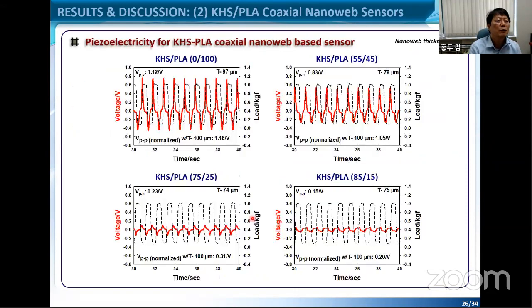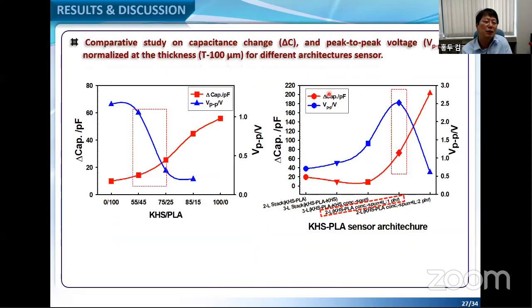value. In terms of piezoelectricity, of course, the PLA 100% gives the highest signal because it is a pure PLA system. But as you increase the KHS, the signal is going to be smaller and smaller. But at about 50%, the signal is not that small. Of course, the absolute value is about 0.8 volt, but it's not that bad. So in this case, 50% KHS and 50% PLA is, I think, one of the good choices. So from this result, I can say that for a coaxial system of PLA with KHS, about 50% KHS is, I think, a good choice.